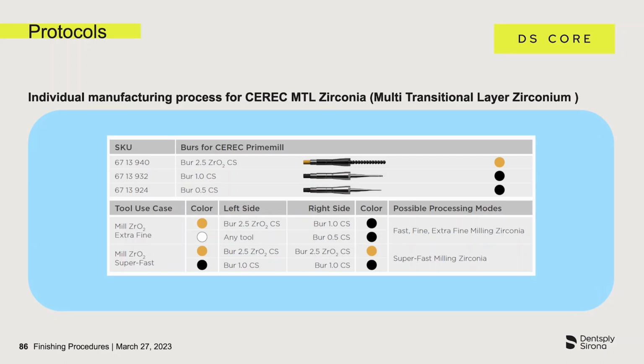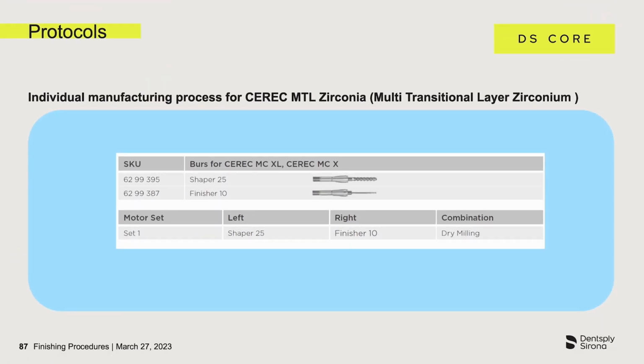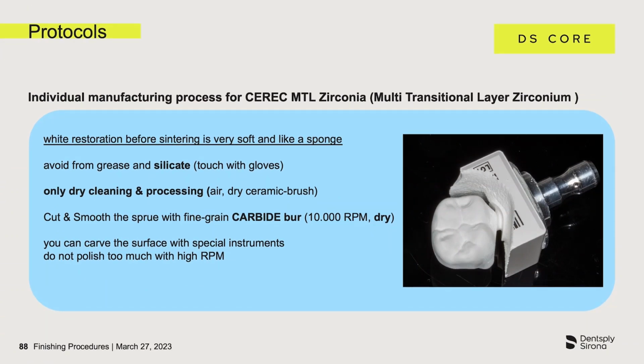The carbide cutter combinations for dry milling of zirconia for Primemill are shown here. Here you can see that in superfast milling mode, each side is equipped with the same cutters to ensure particularly fast processing. This slide shows the instruments for the CEREC MC X and CEREC MC XL. Milling in superfast mode is not possible here. The white restoration before the sintering process is very soft and like a sponge. Therefore, it is imperative to protect it from contamination, especially from grease and silicate particles, and therefore it may only be touched with gloves and should only be processed dry.